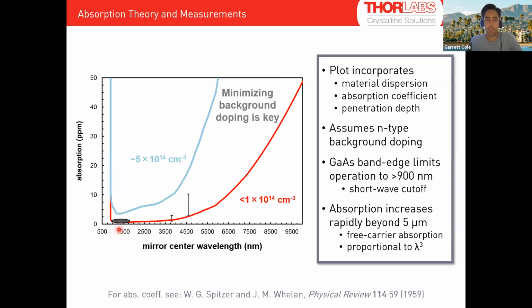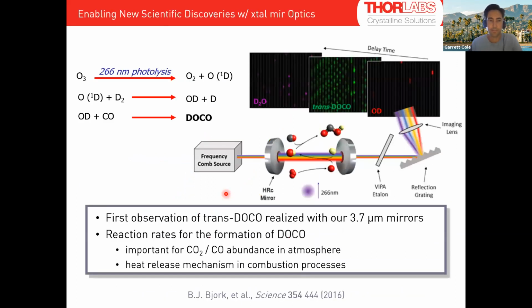So you can see I kind of put a blob over the near IR where we can readily achieve 1 ppm and below. And then in the 3 to 4.5 micron space, we're making good progress here, staying below 10 parts per million there. And it's just working on the epitaxy, optimizing that to get just the purest intrinsic semiconductors possible.